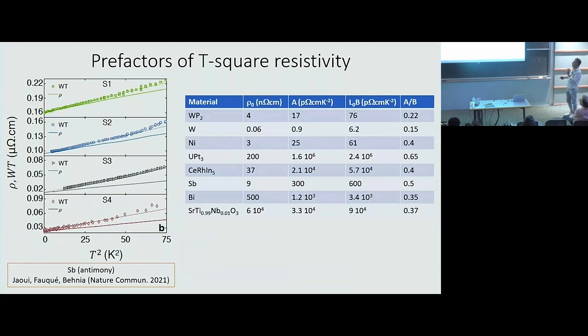To my knowledge, this table summarizes everything which has been measured about thermal transport in different systems. The first thing is that you have a downward deviation from the Wiedemann-Franz law. So if you compare these two prefactors in proper units, you see that B, which is the prefactor of thermal resistivity, is always larger than A. And this ratio is somewhere between 0.15, the lowest ever measured, and 0.65, the highest. So you can talk about the violation of the Wiedemann-Franz law, but this is a very, very...